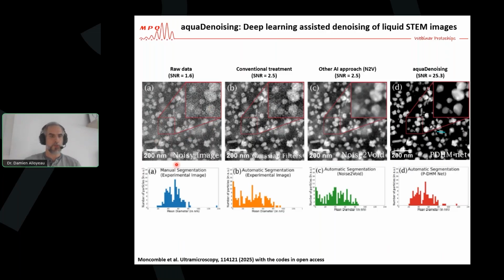So just to show you how efficient it is, I show you here the segmentation of those raw data. You do the manual measurement of the size distribution of those particles. You have a bimodal distribution. When you treat those data with conventional treatment, using a bandpass filter for example, or if you use another type of AI approach to denoise those images, you end up with size distributions that do not look like the one that you obtain manually. But with the AQUA denoising software that we have developed, you are able to obtain this automatic segmentation that is very similar to the manual segmentation, and you can do that automatically.